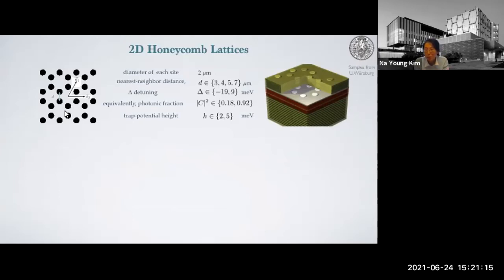That's the beauty of what we can do, because in a real material, to change the lattice constant, either you have to have different devices, or you have to apply pressure or temperature and so on. But in this case, we are utilizing this nanofabrication technique so that we can change the distance, for example, in these 4 different cases.